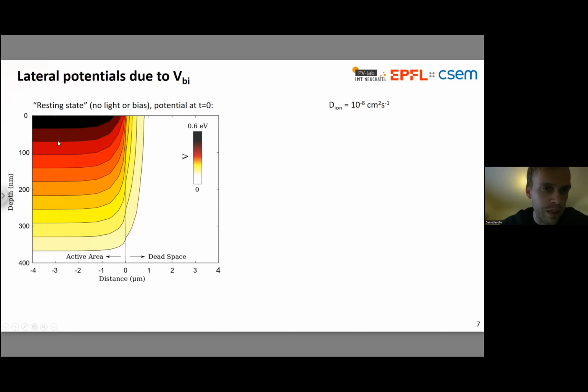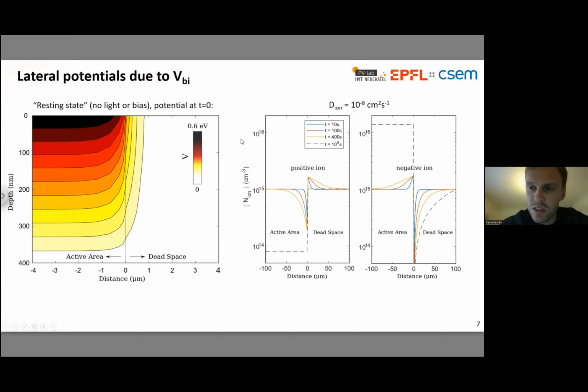So we're very familiar with the built-in field driving ion migration in the vertical direction, so the direction out of plane. And basically now we're just looking at what happens in the other dimension, migration across this boundary. So indeed, once you move forward from t equals 0 and you allow the ions to migrate, you find that depending on what sort of ions we're talking about, whether it's a cation or an anion that's mobile, you can have migration into or out of the active area. And it's happening on time scales which are relevant here.